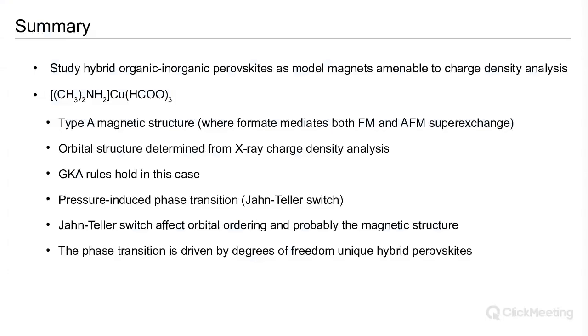So just to summarize. I started off by introducing some background in the inorganic magnets, but I hope I convinced you that there's good reason to pursue these kind of physical problems in the hybrid organic-inorganic systems, if only because we can do charge density analysis to look at the interactions at an unprecedented level of detail beyond the kind of cartoon drawing of the orbitals. I focused on dimethylammonium copper formate 3. We've shown that it had a type A magnetic structure, and in this structure, formate is mediating both ferromagnetic and antiferromagnetic superexchange. But importantly, the charge density analysis shows us that electronically, all the formate is basically the same.